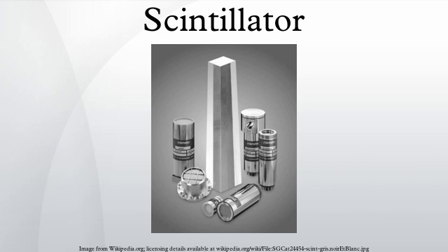Plastic scintillators. The term plastic scintillator typically refers to a scintillating material in which the primary fluorescent emitter, called a fluor, is suspended in the base, a solid polymer matrix. While this combination is typically accomplished through the dissolution of the fluor prior to bulk polymerization, the fluor is sometimes associated with the polymer directly, either covalently or through coordination, as is the case with many Li-6 plastic scintillators. Polyethylene naphthalate has been found to exhibit scintillation by itself without any additives and is expected to replace existing plastic scintillators due to higher performance and lower price.